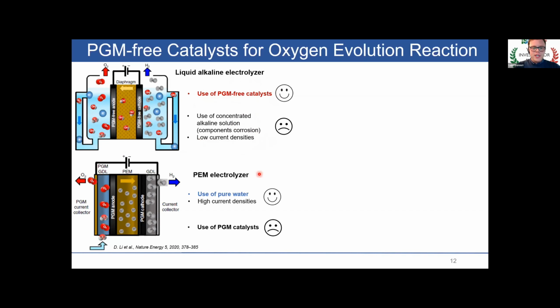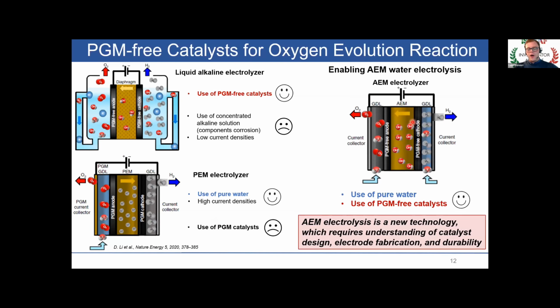On the other hand, the second technology is the PEM water electrolyzer, or proton exchange membrane electrolyzer, which can operate in pure water and at very high current densities, but can only operate with the PGM catalyst due to the highly acidic conditions in the electrodes. Currently, with the development of more efficient and performing hydroxide exchange membranes, we can actually rely on a new technology, which is the anion exchange membrane water electrolyzer, which can potentially combine the two advantages of the previous systems, so the use of pure water and the use of PGM-free catalysts. However, this technology is new and requires understanding of catalyst design, electrode fabrication, and durability.